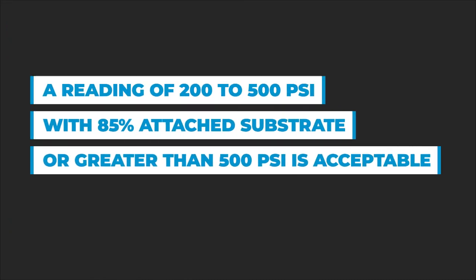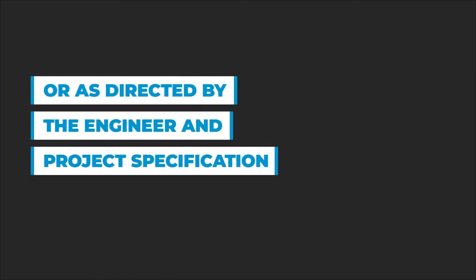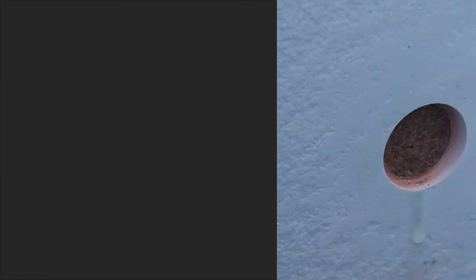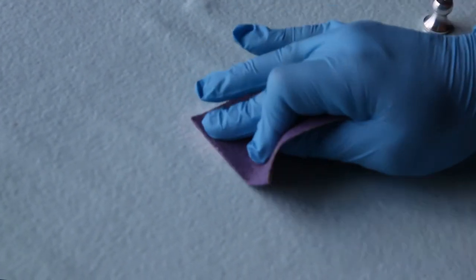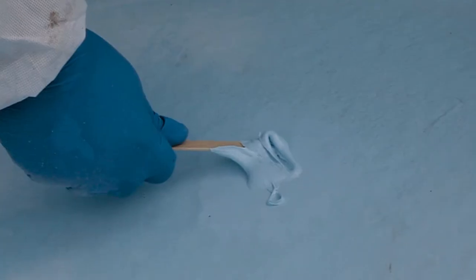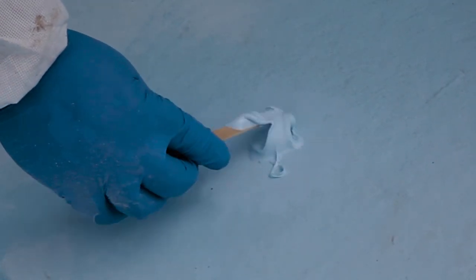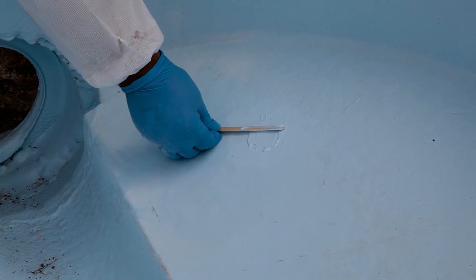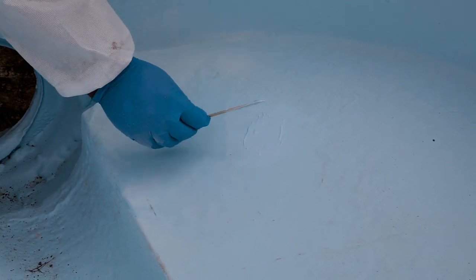A reading of 200 to 500 psi with 85% attached substrate, or greater than 500 psi, is acceptable, or as directed by the engineer and project specification. To make repairs after adhesion pull-off testing, abrade an area approximately 6 inches in all directions. Mix a small amount of coating and apply, taking care to extend the coating across the abraded area.